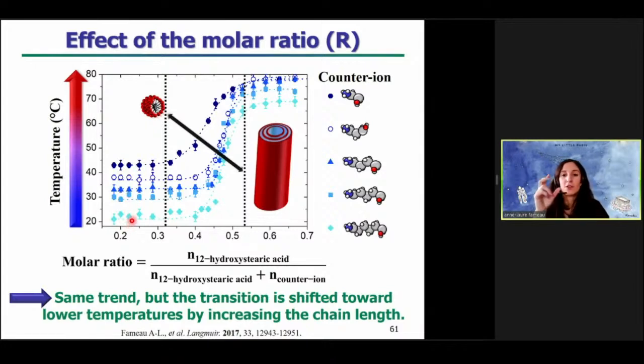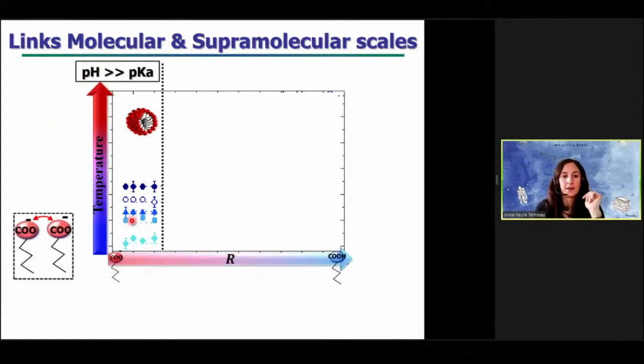So just by tuning the molar ratio and the nature of the counterion, you can really have a wide range of temperature transition between tubes and micelles. But then we wanted to determine what is happening at the molecular scale that can explain this change at the supramolecular scale for this temperature transition between tubes and micelles. For this, we combined different types of experiments: differential scanning calorimetry, WAXS experiments, and infrared spectroscopy measurements.